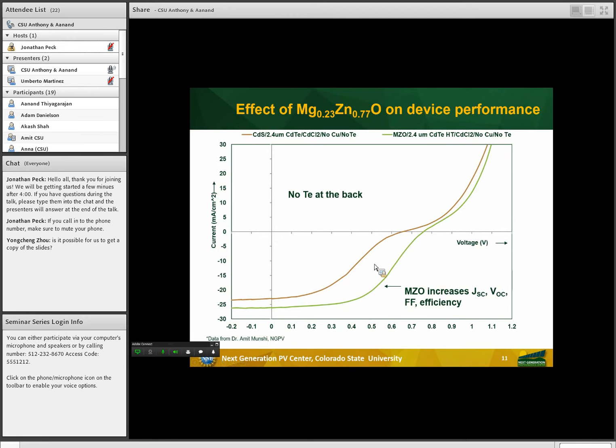shows a cadmium sulfide, cadmium telluride device, which has historically been used by several research groups in cadmium telluride photovoltaics. The green curve shows the IV characteristics of a cadmium telluride device using MZO as a window layer. MZO, with its higher band gap, gives rise to a higher voltage, a higher VOC, and its higher transmission of the solar spectrum leads to a larger current.